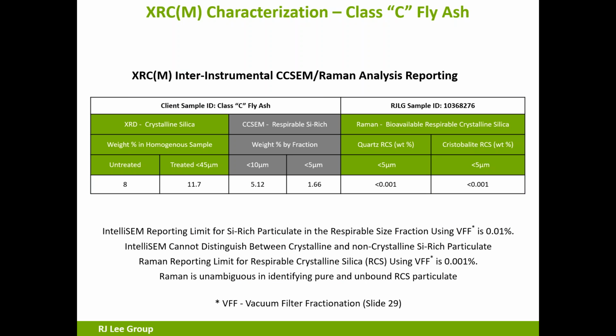So with that data, we start out with our XRD crystalline silica, and we've got the untreated at 8, the treated, which is the less than 45 micron fraction, in this case 11.7. We run that through the SEM, and we then look at how much weight percent there is in a fraction less than 10 and in less than 5 micron fractions, and we get 5 and 1.